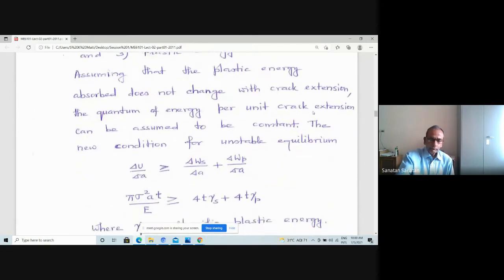What Irwin and Orowan say is that your strain energy is the supply or source of energy, that's fine. But when you are creating a new surface, you just have the surface energy dispersed for unit crack extension, but you must also have plastic energy supplied. As the crack propagates, before the crack propagation or surface extension, it gives rise to plastic deformation.